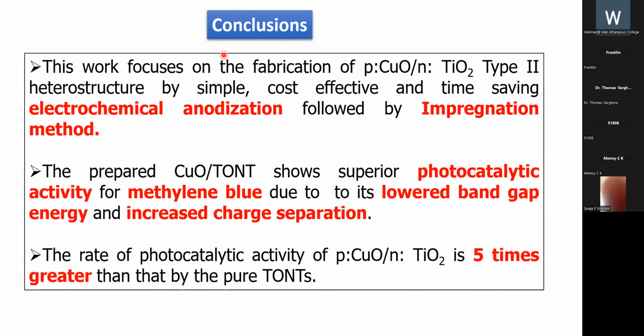Moving to the conclusion, this work focuses on the fabrication of a CuO-TiO2 type 2 heterostructure by a simple, cost-effective and time-saving electrochemical anodization followed by an impregnation method. The prepared CuO TON shows superior photocatalytic activity for methylene blue due to its lowered band gap energy and increased charge separation. The rate of photocatalytic activity of CuO-TiO2 is 5 times greater than that of the pure TON.